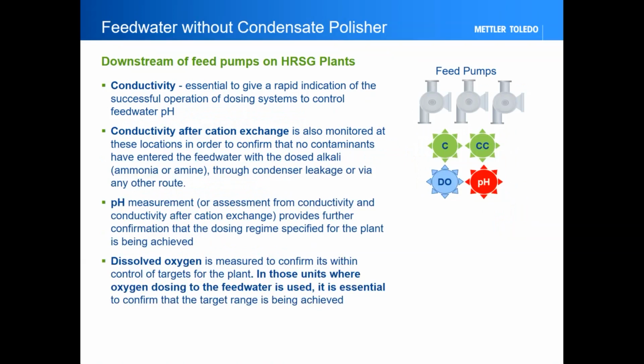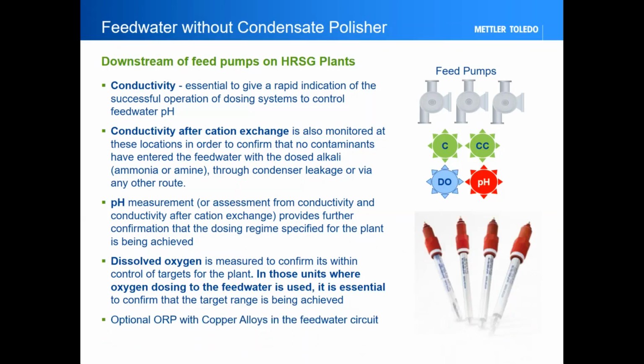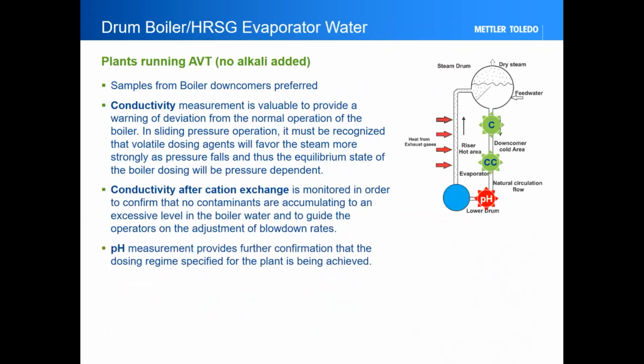Feed water without condensate polisher, again, you want to be making these measurements downstream of the feed pumps, specifically on HRSG plants. You want to be looking at conductivity, cation conductivity, pH, and dissolved oxygen. Those are all the minimum requirements at that sample location for these reasons. I'll point out the comment on dissolved oxygen. Where you're dosing oxygen to the feed water, you really have got to verify you're maintaining the correct dosing of the oxygen. And then again, if you have copper alloys, this is where you would want to use your ORP or your combination pH ORP sensor.